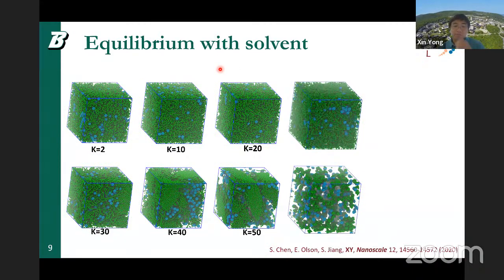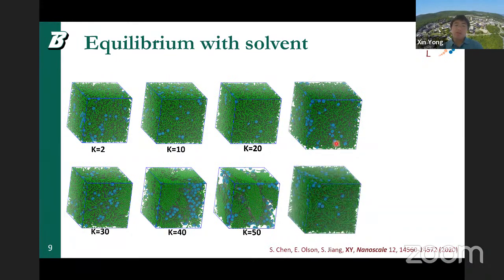So these are two videos, for a very soft polymer and a very rigid polymer. One thing you can notice very clearly is that for soft polymers, the particles are pretty much just randomly dispersed in the matrix. However, when the rigidity increases, the polymer itself starts to form nematic ordering, and the particles try to expel out from the polymer region. In all these states, we consider the polymer to be well dispersed in the solvent, so they like each other with neutral interactions. The polymer and particles slightly dislike each other, so they can still be randomly dispersed. But when the polymer density is too high, the particles will be expelled out.